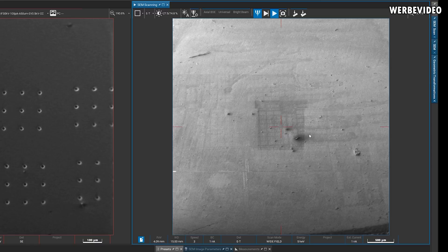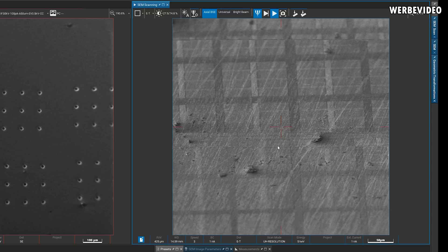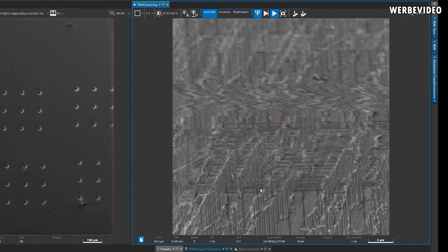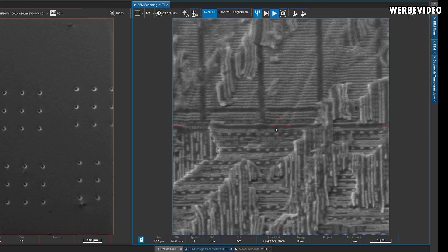Moving on to the AMD CPU, which is more interesting because we ground it down much more — about four or five metal layers remain, compared to about 12 or 13 on the 10900K. Zooming in, you can see residues of interconnects and traces. On the bottom half, vertical lines show the top metal layer, and horizontal lines near the center are another interconnect layer — copper traces connecting parts sitting underneath. On the bottom right, the scale bar shows one micrometer. Keep in mind a human hair is about 80 micrometers in diameter, so this full field of view of 10 micrometers is eight times smaller than a human hair.